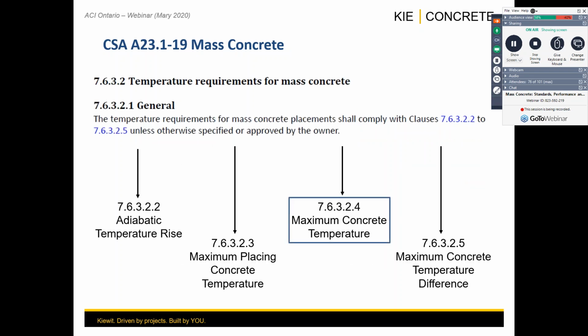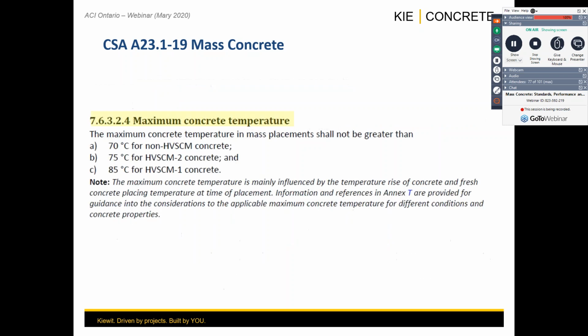The next one is going to be maximum concrete temperature. On the maximum concrete temperatures, we had a lot of good discussions, I believe, during the past few years on what was going to be the most reasonable way of addressing this. Actually, there was no maximum concrete temperature limit in the CSA document. There was only a limit for high strength, where you would limit to 70 degrees Celsius, but there were no limits for mass concrete maximum temperatures.